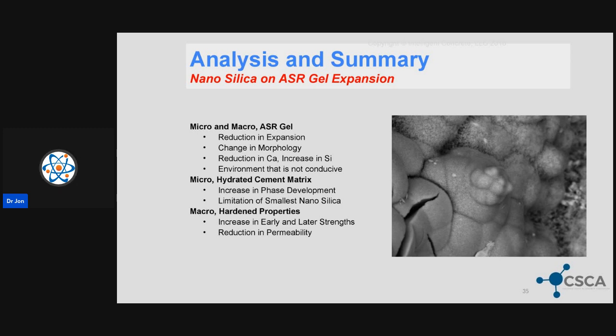From our micro and macro, we noticed the reduction in expansion, change in morphology, that change in chemistry, creating that environment that wasn't conducive. And then ultimately what we found later on throughout the rest of the research, when you get into my PhD, is we changed the phases of the calcium silicate hydrate, specifically the silicon tetrahedra in that calcium silicate hydrate, implying that the overabundance of silica not only treated that pessimum to get past the point where the ASR wanted to thrive and survive, but we're creating a stronger matrix that'll be more resilient to that expansion when it does occur.